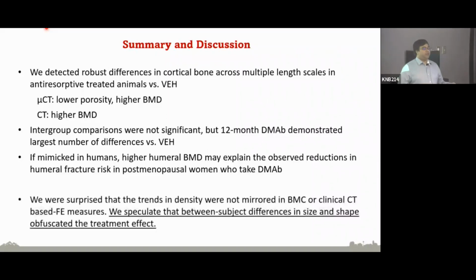However, I will end on this note: we were certainly surprised that we didn't see these trends in bone mineral density reflected in things like bone mineral content or the clinical CT measures of finite element models. I don't think my conclusion here is that antiresorptive treatment doesn't make bone stronger. I think really what's happened is that the design of our study, the cross-sectional nature, wasn't able to separate the between-subject differences in size and shape from the treatment effect. So that's my personal opinion about that.